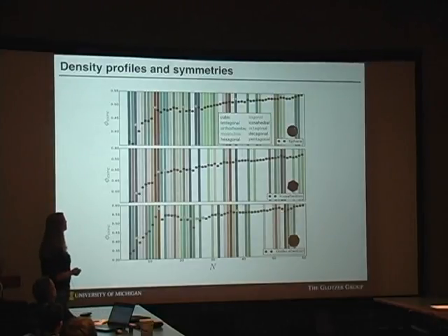You can line these up on top of each other for all of these different particle types. These are the two most spherical platonic solids, and you can do a similar kind of analysis. Something to note here is that we see some developing patterns in the data. At certain values of n, the crystal class is the same, and even the point group symmetry usually is the same for these clusters. At certain values of n also, the magic numbers are the same. So n equals 6 is the same for all of these.